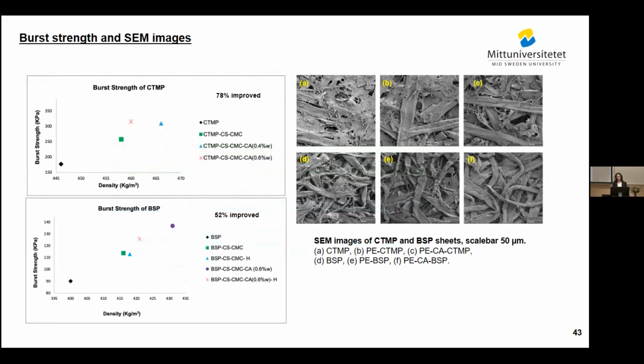Burst strength of any material is one of the important properties that show the resistance of this material against rupture. And for paper as a primary constituent in packaging material, it's better to have this good property. Then with this method, we could increase the burst strength of CTMP by around 78%, and for bleached sulfite pulp, around 52%.